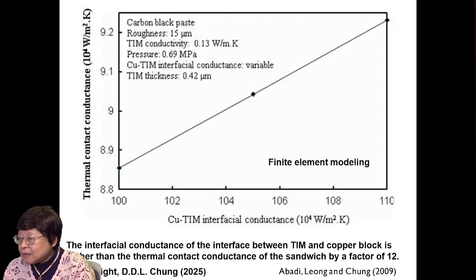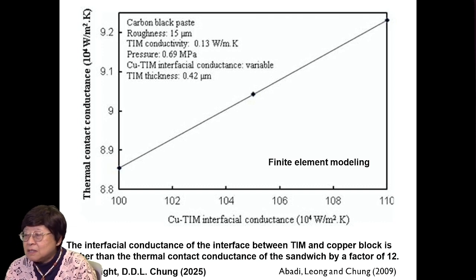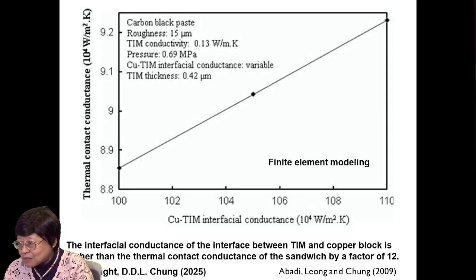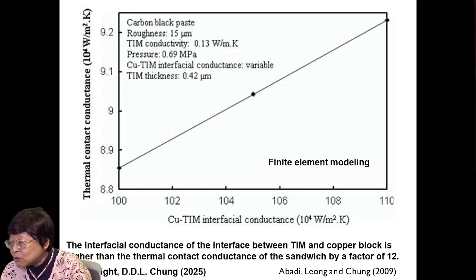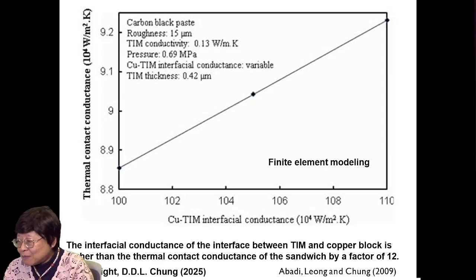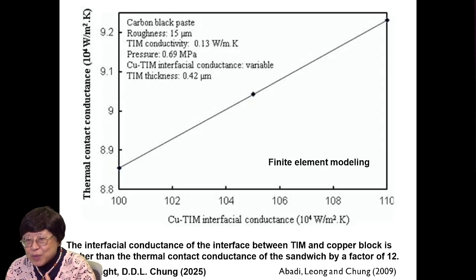Here shows the interfacial conductance of the interface between the TIM and the copper block, which is the mating material, the adjoining surface. This interfacial conductance is shown on the horizontal axis, whereas the overall thermal contact conductance of the sandwich is shown in the vertical scale. And the two relate, obviously. But note that the interfacial conductance is higher than the thermal contact conductance of the sandwich by a factor of 12. So we have to make sure that when we read a paper, we are distinguishing between these two parameters.